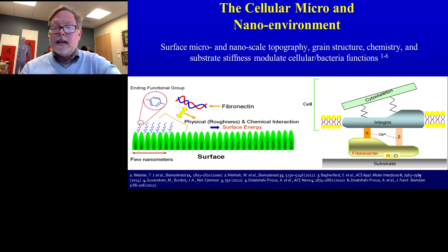If you then take that titanium and put these nanoscale features on there, like what's diagrammed in green, you have now increased the amount of titanium that's exposed. That increased amount of titanium, increased surface area of titanium, leads to different surface energy. More exposure of a hydrophilic chemistry will give you more hydrophilicity.